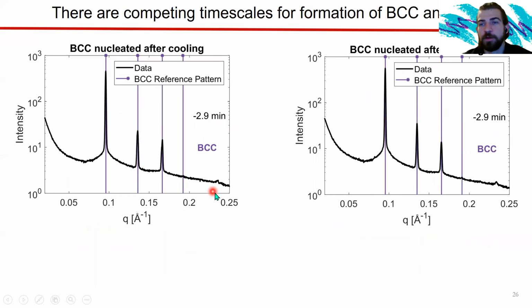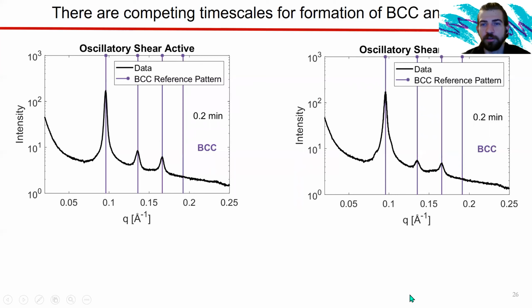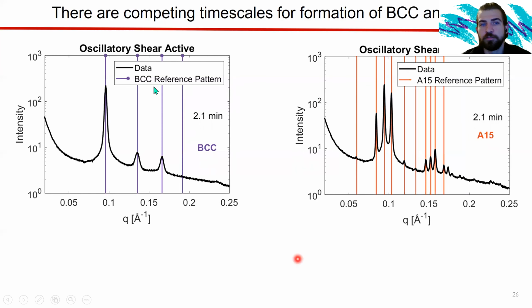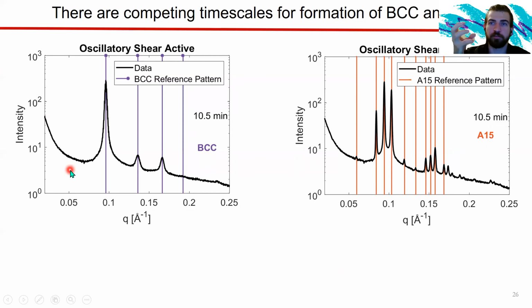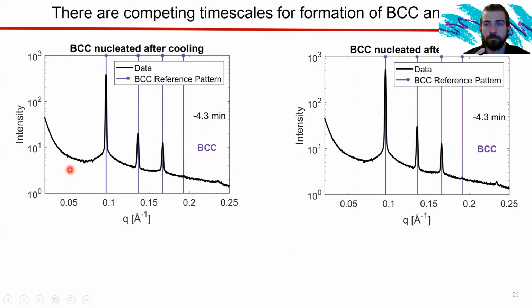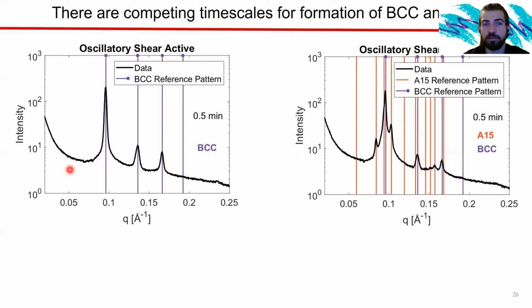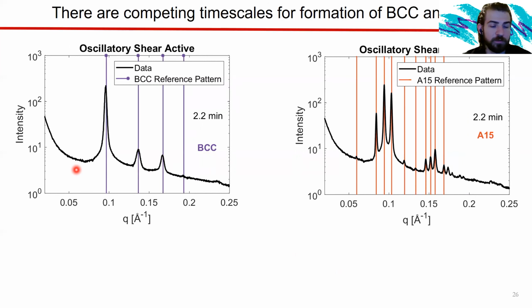So here we have two different GIFs on the left. On the right, we have different shear conditions. And you can see that under these conditions, we don't have any A15 forming at all. And on these conditions, we only have A15 forming. So we're able to tune our oscillation parameters to get the phase behavior that we're looking for, at least the transition rate that we're looking for. These are the two extreme cases that we found during our experiment.